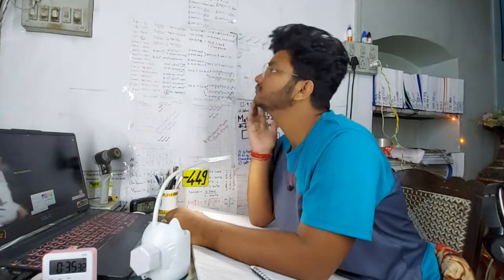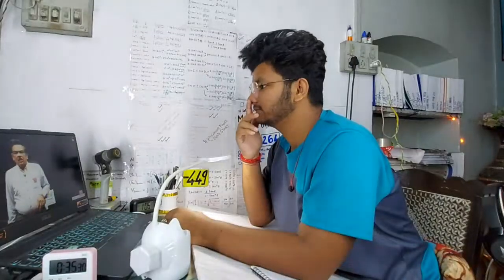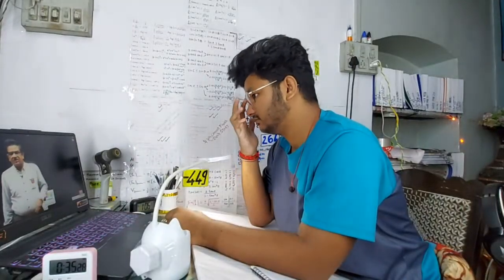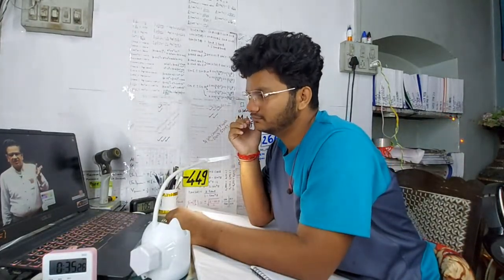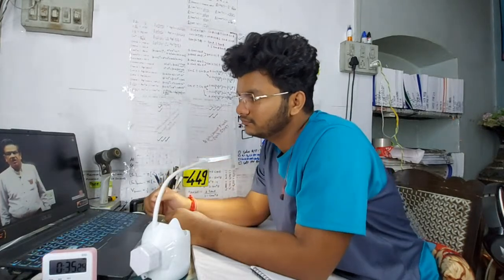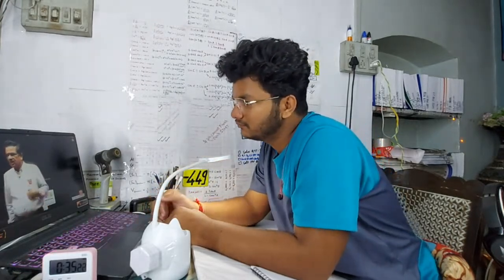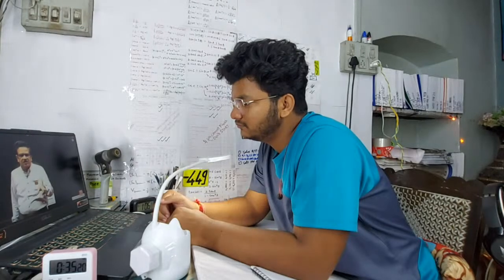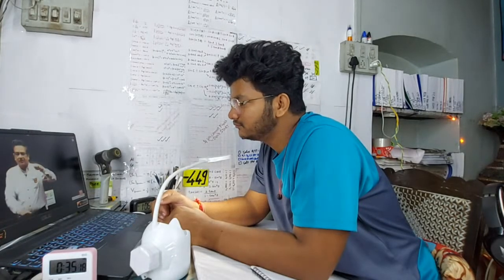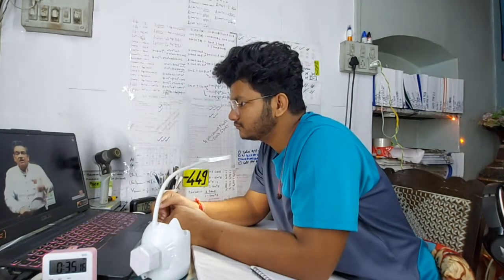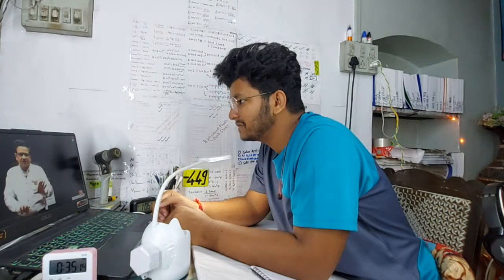Girish, look at the screen. I'm in front of you. Austenite to martensite transformation has two characteristic temperatures. Number one, martensite start temperature. Number two, martensite finish temperature. If you are quenching the specimen only up to room temperature and the martensite finish temperature is below room temperature, then definitely there will be martensite plus retained austenite.